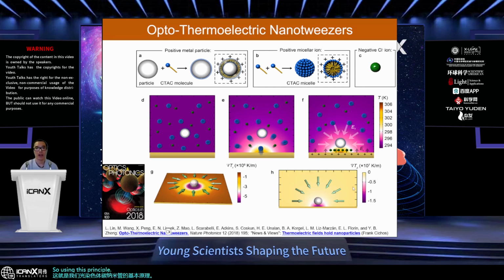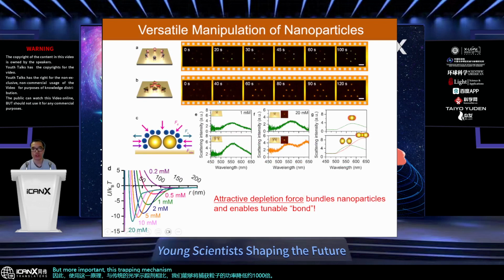Using this principle, we are able to reduce the power for trapping the particle by about 1,000 times compared with conventional optical tweezers. But more importantly, this trapping mechanism can apply to all sorts of particles. In traditional optical tweezers, it's very challenging to trap metal nanoparticles, in particular at wavelengths close to the plasmonic resonance. As I just mentioned, because of this plasmonic excitation, the particle becomes very hot. Under this heated condition, the Brownian motion becomes so strong that trapping becomes almost impossible. But using our mechanism, we are able to show that we can trap all types of particles, including metal nanoparticles at plasmon resonance wavelengths.